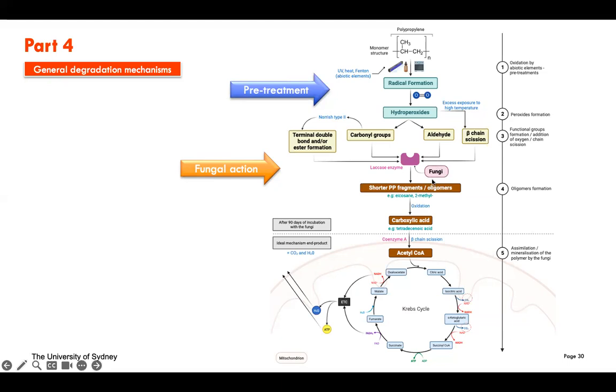And then the fungi will act on the surface of this polymer by the action of enzymes. In this research, I only focused on laccase enzyme because I found in the literature that laccase is one of the most prominent enzymes responsible for the degradation of polypropylene or any types of polyolefins or synthetic polymers. But there are also other types of enzymes. I know more than 10 types of enzymes that are able to degrade large chain polymeric materials. Among them are manganese peroxidase or lignin peroxidase.